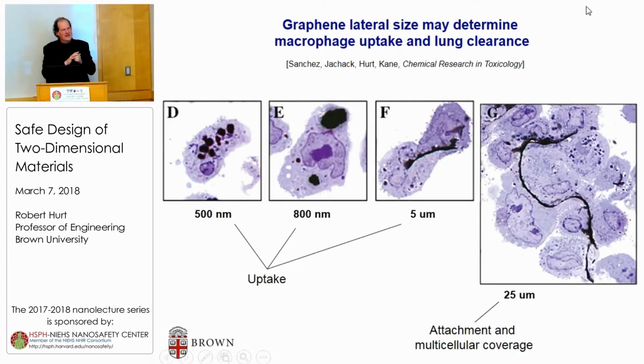And for 2D materials, a lot of that seems to be associated with the lateral dimension. If you look at very small lateral dimension graphene flakes, they're taken up, in this case, by macrophages easily. And as the lateral dimension grows, it gets more difficult. Even 3 or 4 micron sheets can be taken up. But if you get to very large sheets, they obviously can't be taken up by a single cell, and you get these multicellular constructs that surround the flakes that may be the beginning of a granuloma. And so there's a lot of interest in understanding the effect of lateral dimension, and at what point for a 2D material does the size grow to the extent that it becomes very challenging for cells to process? And it's a bit like the problem with carbon nanotubes, in that these are very thin. So even large flakes can have a small aerodynamic diameter, which governs the settling velocity in the lung, so it can be respirable. But the long lateral dimension makes them difficult to process.